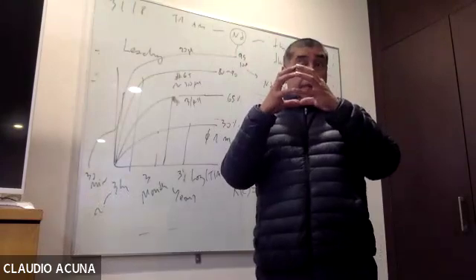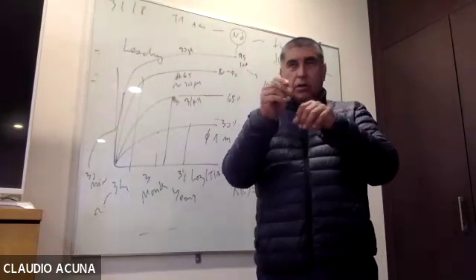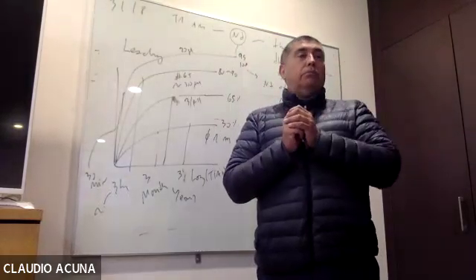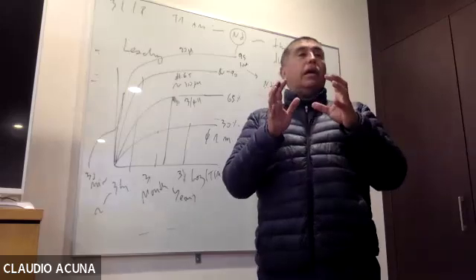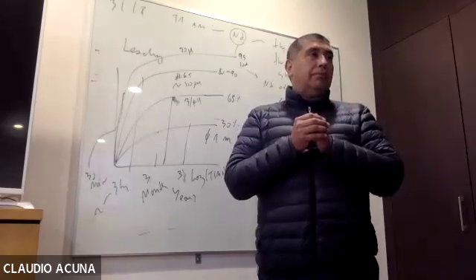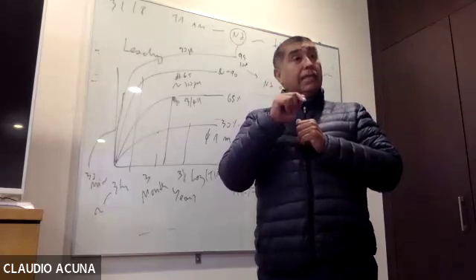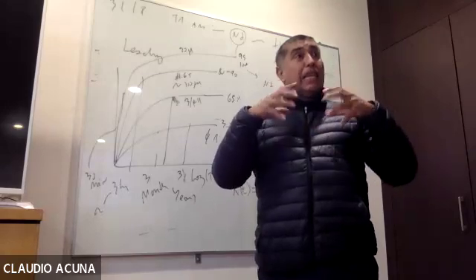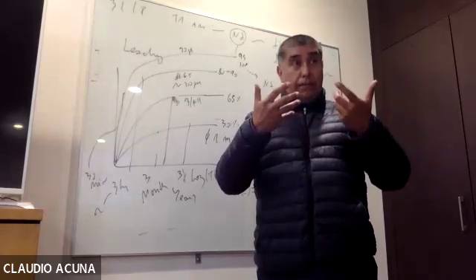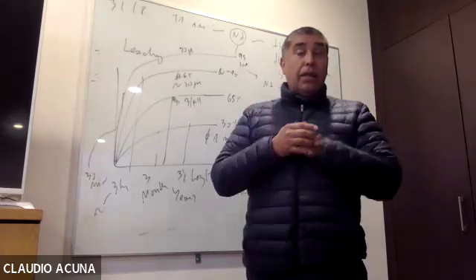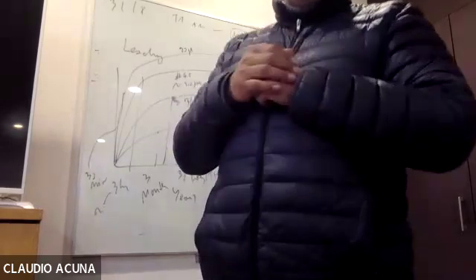If I take the same crystal, crush it, grind it to 1 micron, it will take 10 minutes and 100% recovery. So in this case, the size influences the interfacial area. We want to add another experiment because it's very simple, you know that? The dissolving of coarse and fine salt. Remember we did it once?